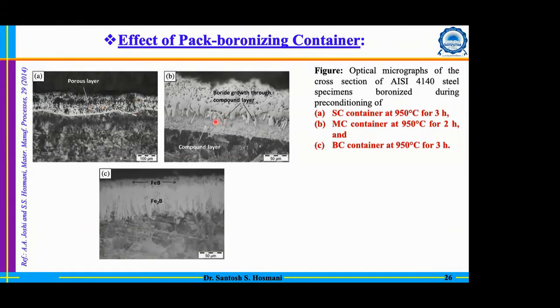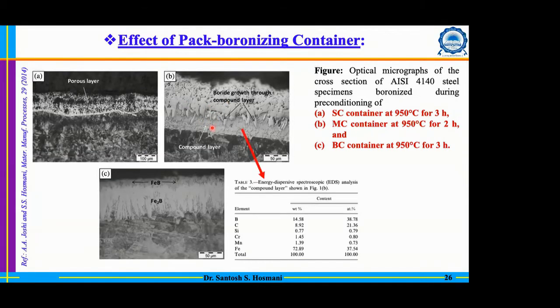In the case of figure B, we have about 2 hours. Temperature is the same in all cases. There we have seen the compound layer formation. And the EDS chemical analysis shows that we have very high boron as well as carbon content there. The hardness value shows only a slight increase. The core has about 300 HV hardness, and this compound layer has about 400 HV hardness.